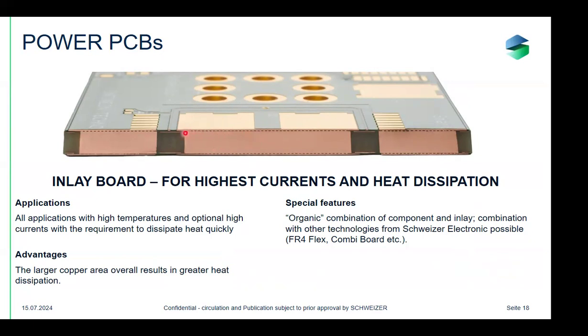So with this cross-section of 2 millimeters in thickness and maybe 10 to 20 millimeters in width, you can provide a really good cross-section where you can run more than 1000 amps with a very low resistance to your components and back. This is used for a battery switching device, where you can handle more than 1,000 amps over one PCB. So the major electrical resistance is coming still from the components and not from the PCB.